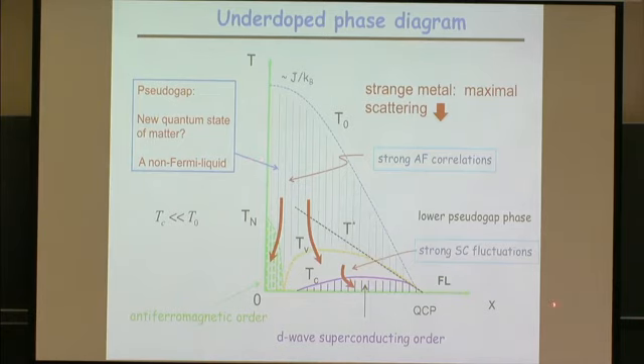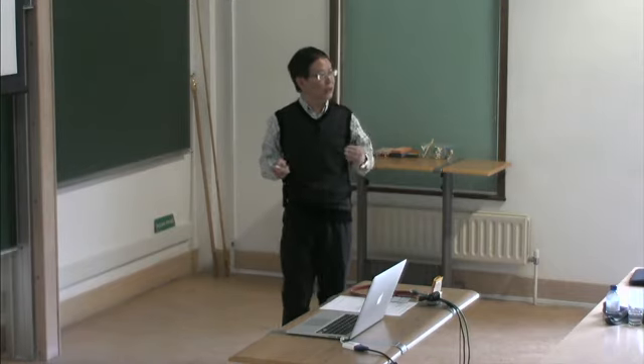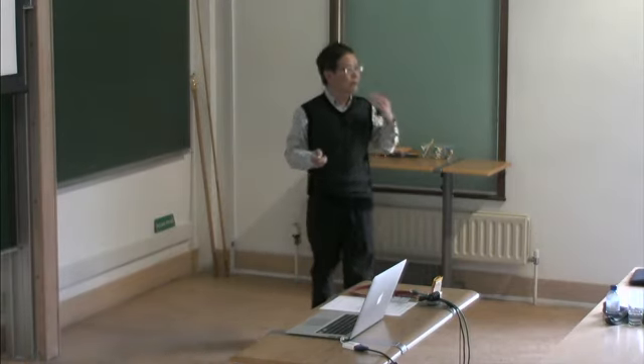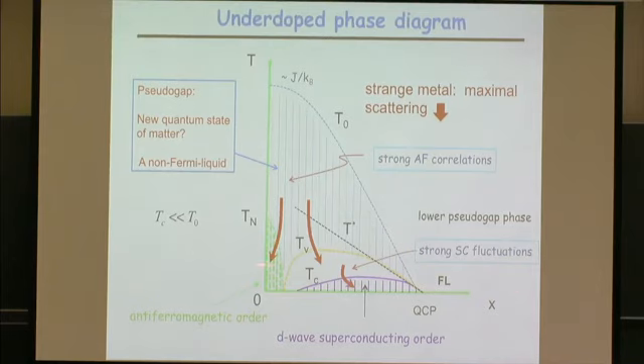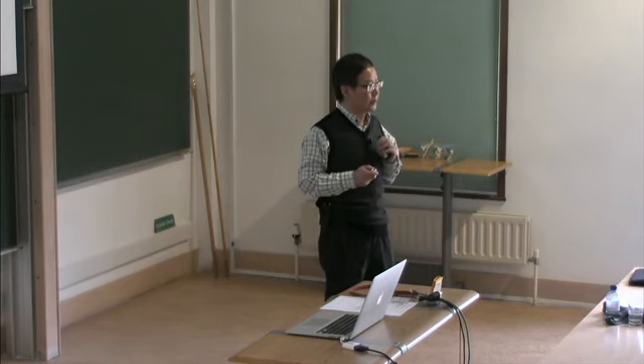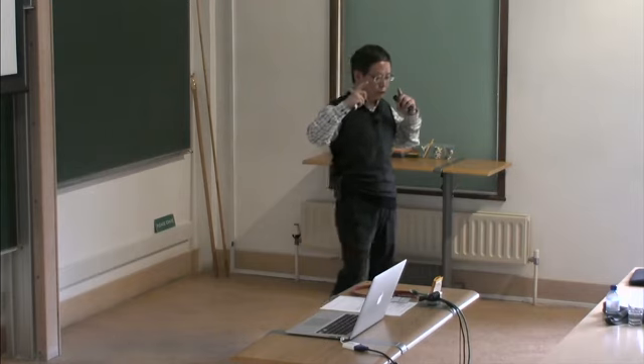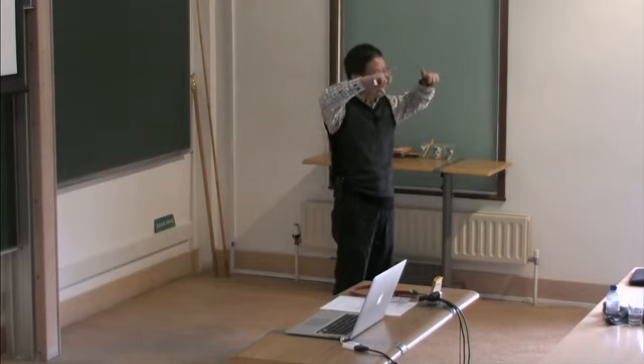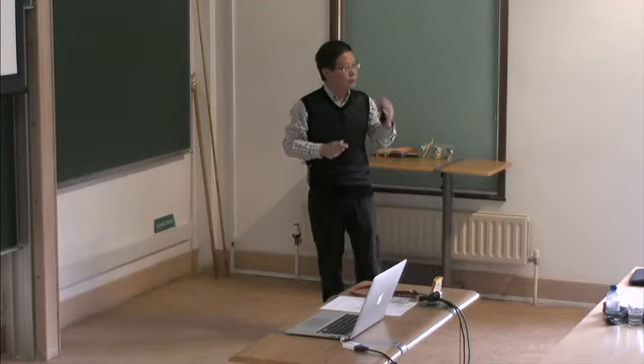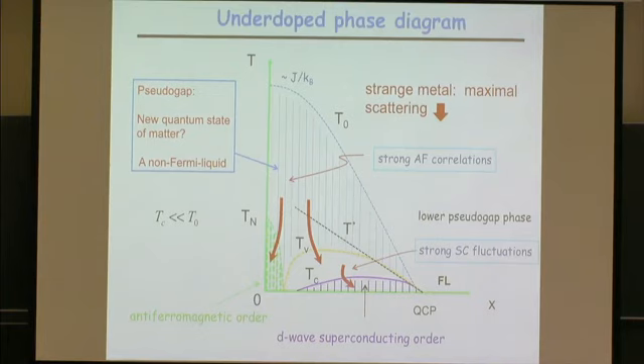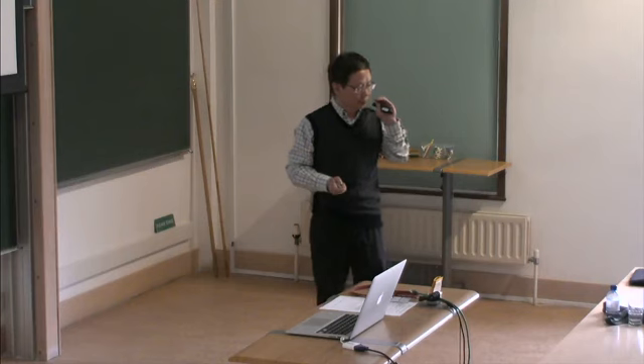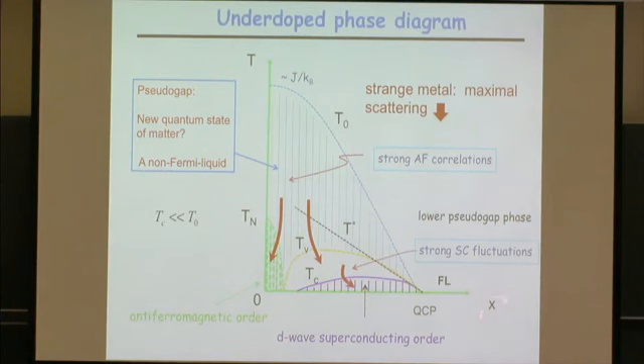And especially the horizontal axis: in other materials, you can change not only the charge concentration but also pressure or isovalent concentration, and you get a similar phase diagram. But here, the universal behavior is controlled only by this x, the charge concentration. In a Fermi liquid, the actual charge number is not that important. The important thing is the density of states at the Fermi surface. So when you change the charge carriers, you only indirectly influence the density of states via the Fermi energy. But in the cuprates, all these measurements show that different properties sensitively depend on this x.